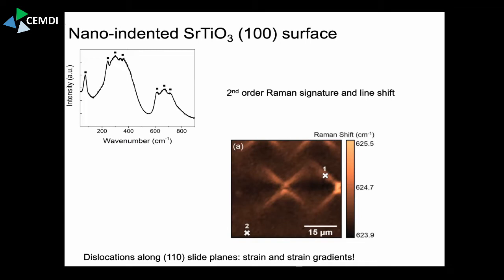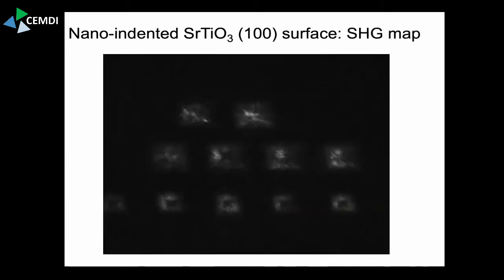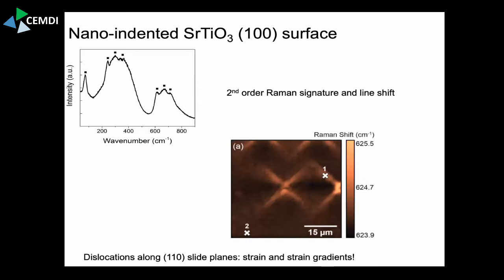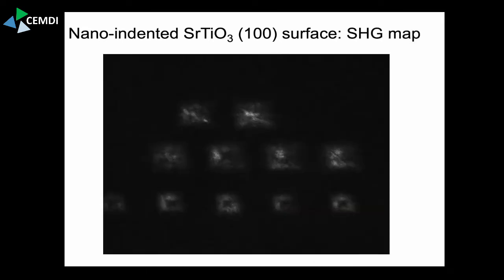And that was the moment when we went to see François Légaré and said, can we please do second harmonic generation on these samples? And that was done. And what you see, there's bad contrast here, my apologies for that, is that we had multiple of these indentations. And in this picture, I hope your eyes are better adapted than mine to the darkness here, you see these dark crosses in the center, always. And where you have the maximum strain, there is no gradient. That's why you have these dark crosses in the middle.